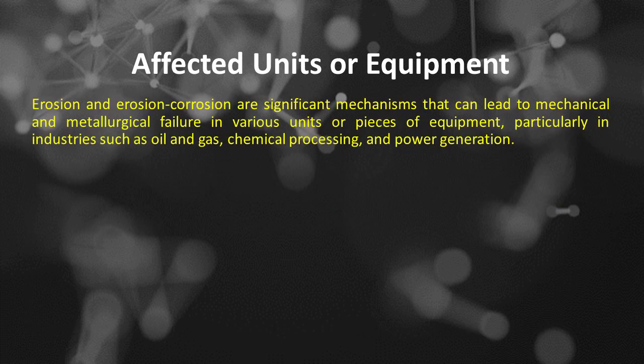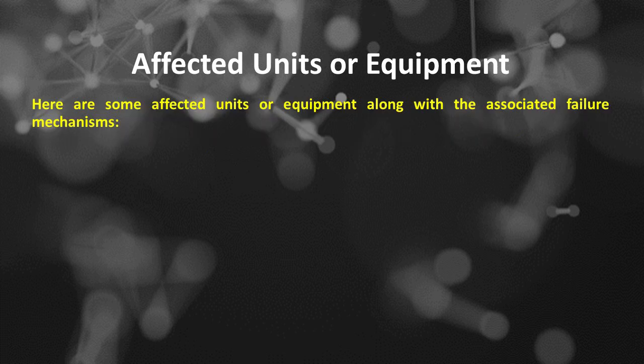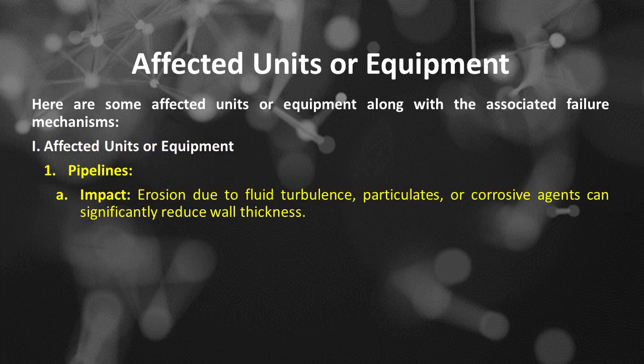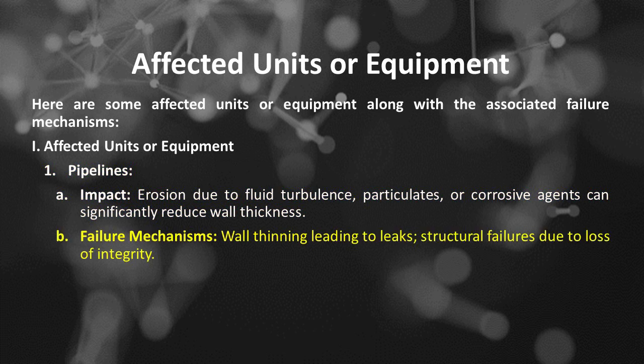Erosion and erosion-corrosion are significant mechanisms that can lead to mechanical and metallurgical failure in various units or pieces of equipment, particularly in industries such as oil and gas, chemical processing, and power generation. Here are some affected units or equipment along with the associated failure mechanisms. Number 1 of affected units or equipment is pipelines. The first is impact: erosion due to fluid turbulence, particulates, or corrosive agents can significantly reduce wall thickness. The second is failure mechanisms: wall thinning leading to leaks, and structural failures due to loss of integrity.